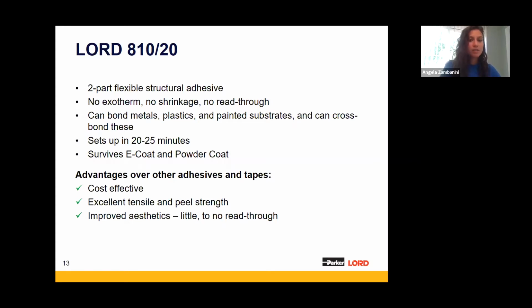It also doesn't have an exotherm, has no shrinkage, and can bond to a wide variety of materials, including metals, painted metals, plastics, and substrates, and it can cross bond to all of these. The Lord 810 sets up very quickly, so you get about 8 to 10 minutes to work with it, and then in just 20 to 25 minutes, you can unclamp your parts and send them along into final assembly or further along the line. The other great thing about this product is it can survive e-coat and powder coat. We get that question a lot: can your adhesives go through powder coat or e-coat, or through a bake oven?